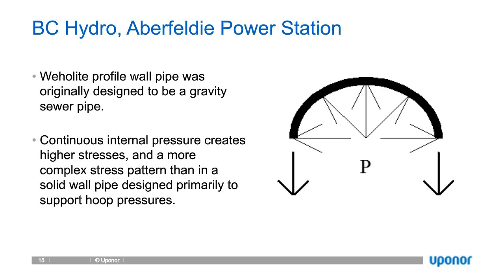Figure 2 in this slide illustrates the pressure balance within a solid wall pressure pipe. The vertical component of the pressure across the center line at ID in the upward direction is balanced by a downward pressure in the pipe wall for a given unit of length. And it's usually assumed to be uniform pressure within the pipe wall. In the steel industry, this relationship is known as Barlow's formula and is typically referred to as the ISO formula in the polyethylene industry.